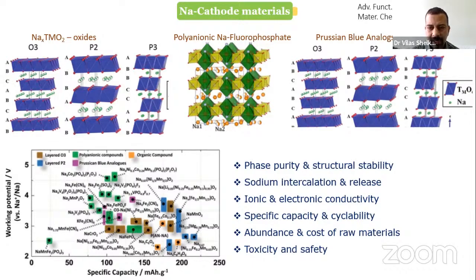Second important thing is structural stability, because when you make these materials, the structure should remain stable, particularly when the sodium ion is intercalated or released from the structure. For many applications, the structure is stable because you don't remove any ion or any atom from the structure. But in this case, essentially the sodium ion has to go from cathode to anode or anode to cathode. So during this transport of sodium from one end to the other end, the structure should always remain stable. It can tilt a little bit, but nevertheless, along with its tilting, it should keep its stability for sodium ion accommodation and sodium ion release as well.